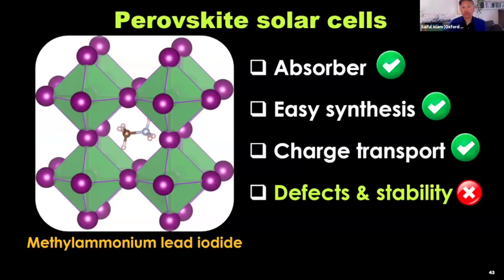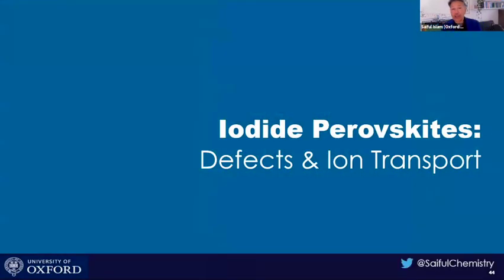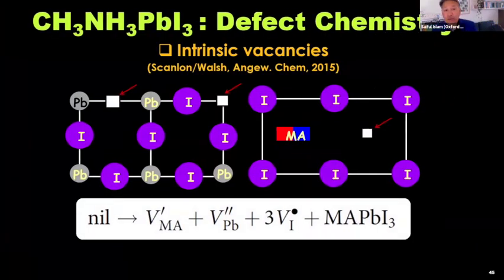However, there is a problem with these perovskites. They absorb well, they're easily made, they've got good charge transport. However, their long-term stability and their defect properties are a problem. So we wanted to get some atomic scale insights into why. We started off by looking at their defects and ion transport. And it was elegant work of David Scanlon, Aron Walsh and others, very early work, that found that they are intrinsically defective with mainly vacancy disorder in the bulk. I'm showing you the equation at the bottom. V is for vacancy, not vendetta. V is indicating that there are vacancies in the structure, which I've highlighted with red arrows.